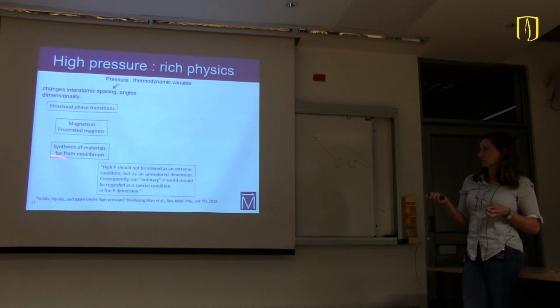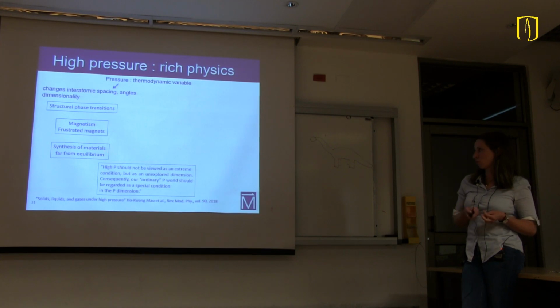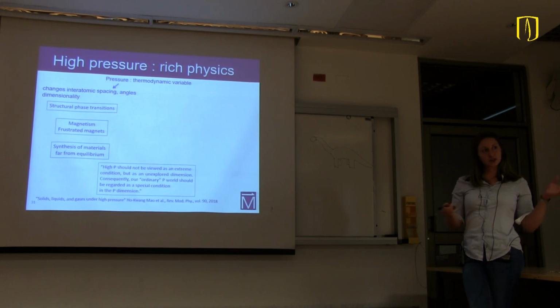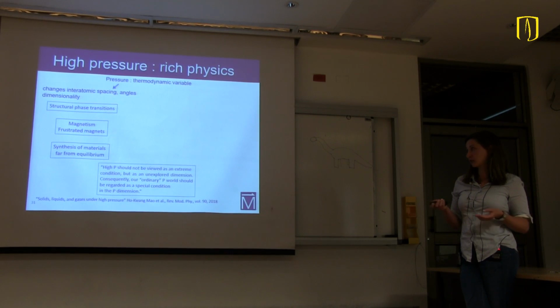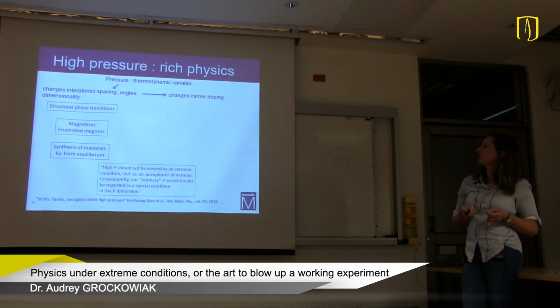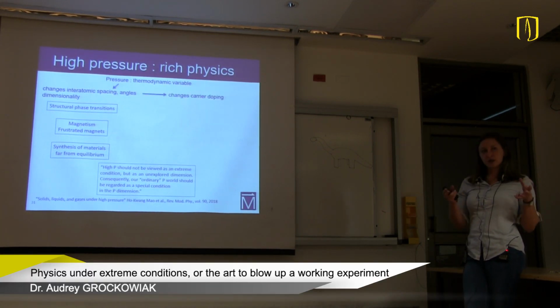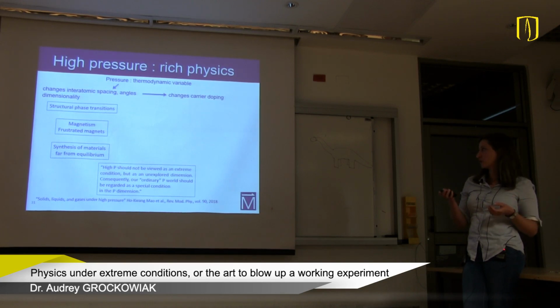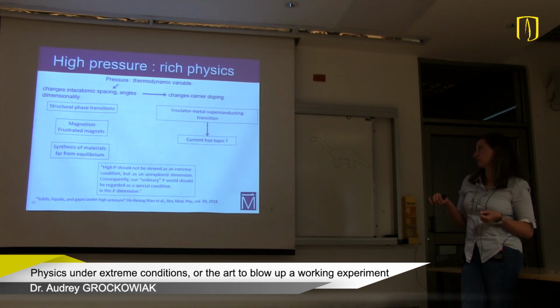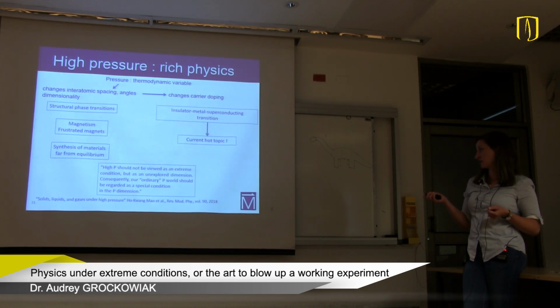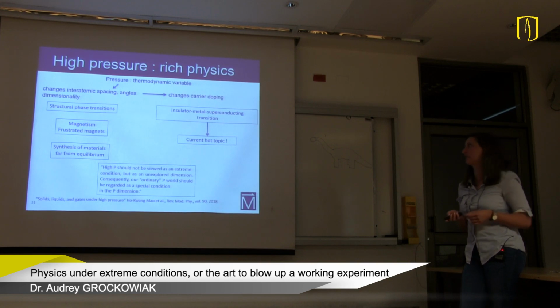And a growing area of interest right now is the synthesis of materials far from equilibrium. You can pressurize a sample, you can laser heat it, and you can create something that's completely different, far from equilibrium. Also, by bringing closer together the various ions in your system, you can change the carrier doping. So you change the density of carriers inside your sample. And you can go from an insulator to a metal to a superconductor transition. This is one of the hottest topics right now in high pressure, and I'll talk more about that later.